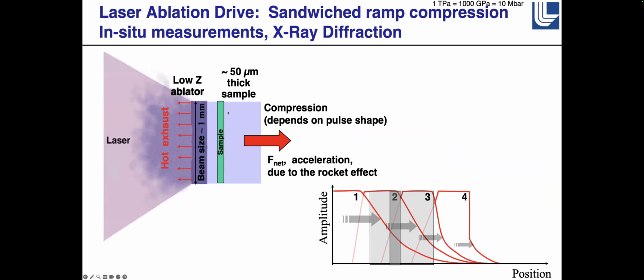So after we did that work, it became very clear. I was highly suspicious that we would be able to get to megabar pressures with single crystals. And so I really wanted to develop a technique for getting samples that were powder samples to compress. And I also wanted to ramp compress them so that we wouldn't shock melt everything at a megabar or two. And so what we came up with was a low Z ablator, like I already talked about, the rocket effect to drive a wave through our sample.